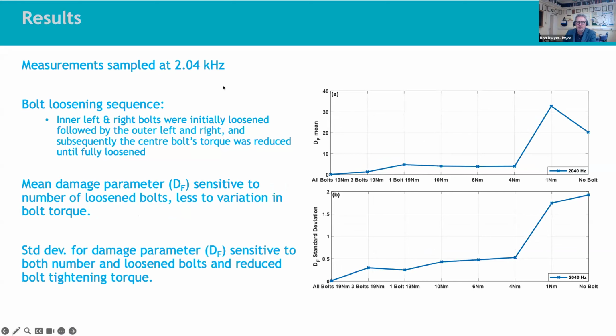Generally, the resonant frequency of this structure is in about this region. It's in the kilohertz region. So these sensors should be fast enough to sample that. But in this instance, it didn't quite get the reduction in torque on the bolts here, although it could predict when the bolt was fully loosened.